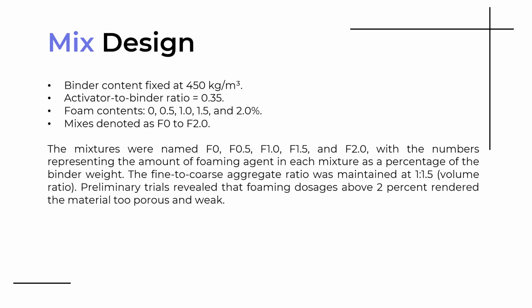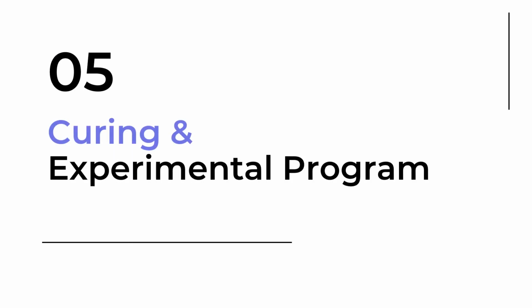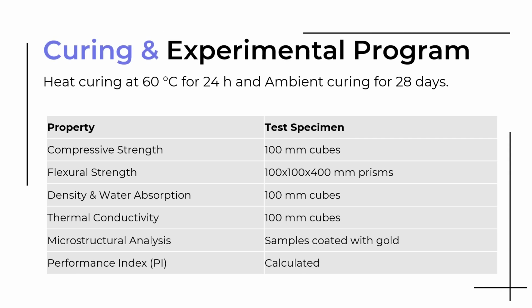For the design, the binder content was fixed at 450 kg, with activator to binder ratios around 0.3 and 0.35, and the foaming content was varied at different ratios between 0 to 2%, and mixes denoted as F0 to F2. For the curing and experimental program, we heat up to 60 degrees centigrade for 24 hours to ensure good heat curing, and then we do ambient curing for 28 days.